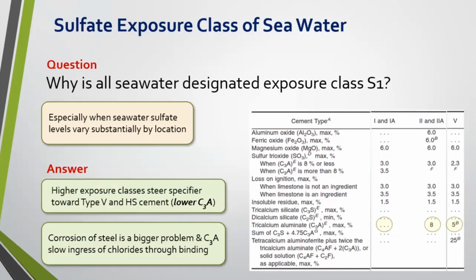So when you talk about the sulfate exposure class of seawater being S1, the chart on the right here is an excerpt from ASTM C150. And in C150, there are 5 different types of cements. We'll get into this a little bit further in a minute. But types 2 and 5 are specifically moderate sulfate resistance and high sulfate resistance. And you'll notice at the bottom of the chart that the primary difference between these is the maximum content of C3A, or tricalcium aluminate: 5% on a type 5, 8% on a type 2.